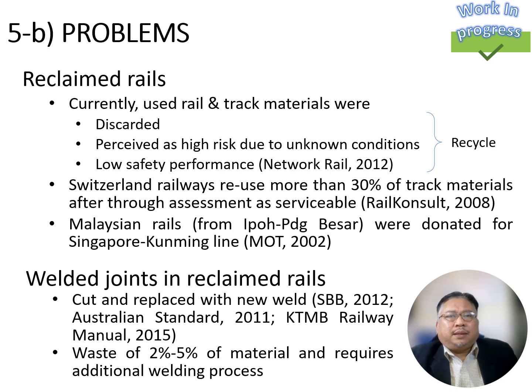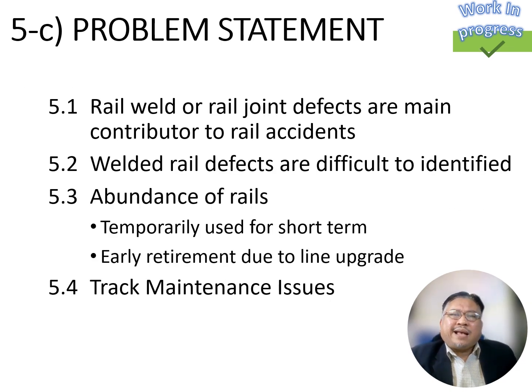In regard to the welded joints in reclaimed rails, it has been the practice to cut and replace them with a new weld. This is considered a wastage of 2 to 5% of material, and it requires an additional welding process to rejoin the cut rail. So the problem statement escalates around the industry: rail weld or rail joint defects are a main contributor to rail accidents.